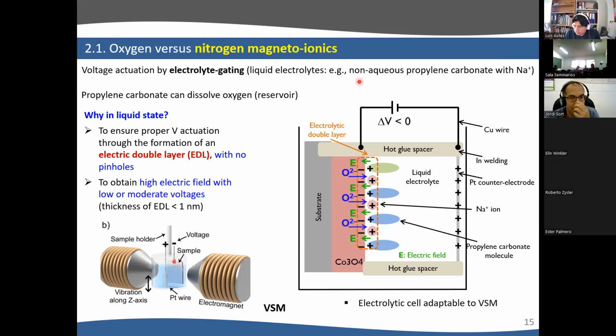And this propylene carbonate contains traces of sodium, which allow to form the electric double layer. And this is very interesting because the electric double layer is a very thin dielectric layer that forms at the interface between the material of interest and the liquid, and it is very narrow. It's only 1 nanometer, which means that we can induce ultra-high electric field with moderate voltages. Remember that electric field in a capacitor is voltage divided by thickness. So here with such a small thickness, we can generate very large electric fields with moderate voltages.